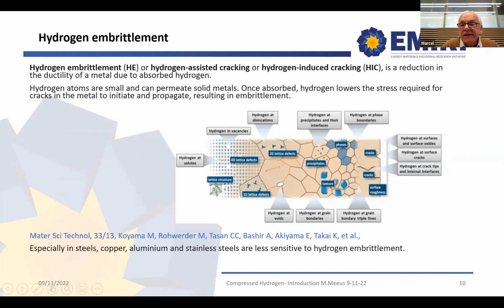A word that has been mentioned already a few times is hydrogen embrittlement. Hydrogen embrittlement, or hydrogen-assisted cracking, hydrogen-induced cracking, is a reduction of the ductility of a metal due to absorbed hydrogen. Hydrogen atoms are indeed quite small and can permeate through solids. And once absorbed, hydrogen lowers the stress required for cracks to be initiated and propagated into the metal, resulting in embrittlement.